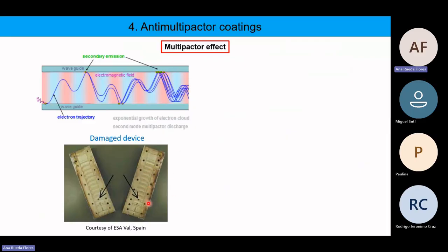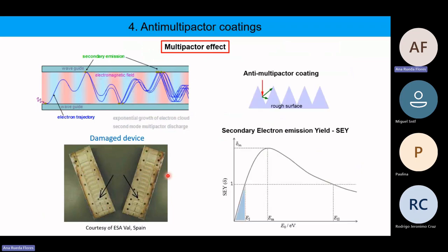And this is what you can see here. This is a picture given by the European Space Agency, and you can see that in the edges of this waveguide, we can see damage, that the material has been burned. So one possibility to decrease this phenomenon is to have a corrugated metallic surface in the nanoscale. So when the new secondary electrons are created, they can travel just a short distance, which means that they can be accelerated just a short time. They can gain energy just a little till they crash again. And as the new secondary electrons always start with low energy, if you don't give them enough space or enough time to be efficiently accelerated, the phenomenon disappears.